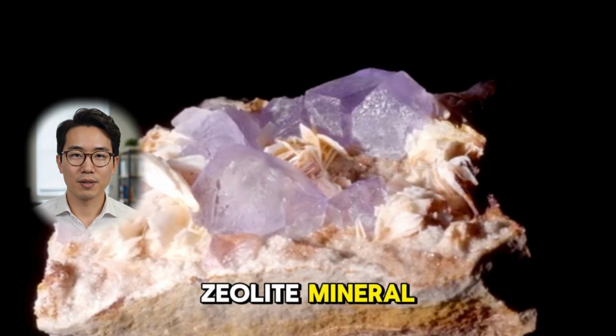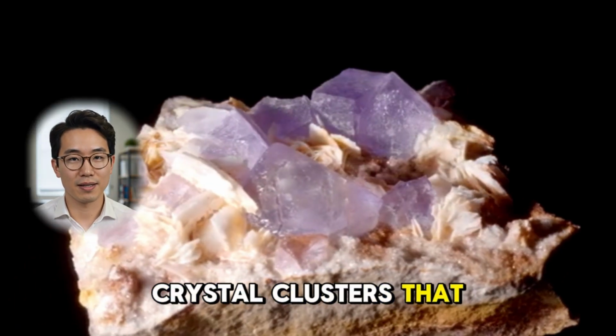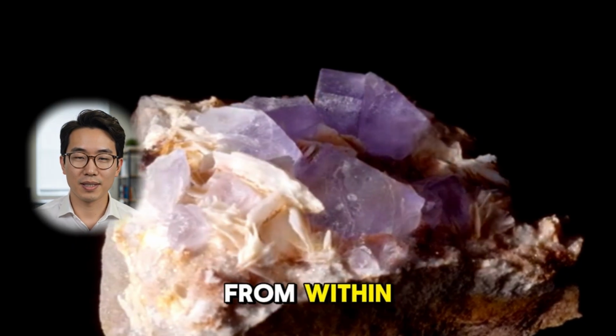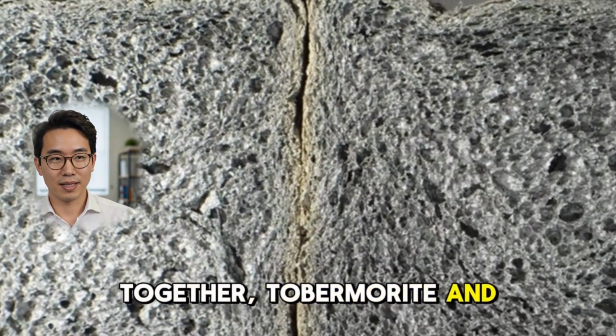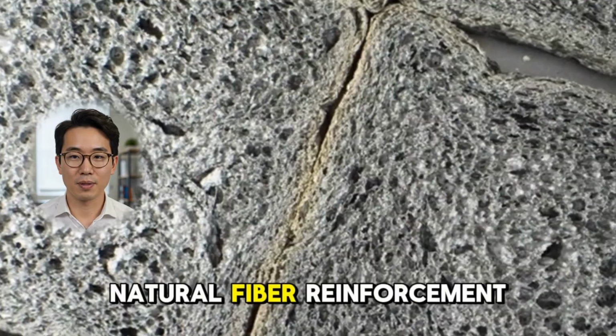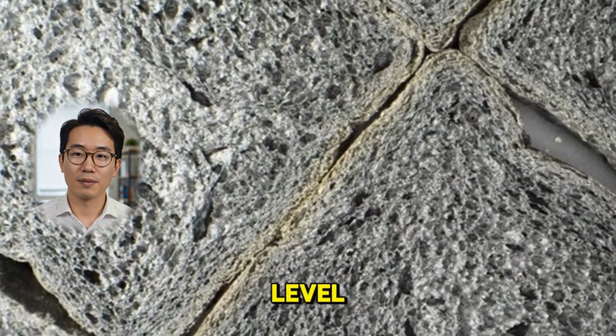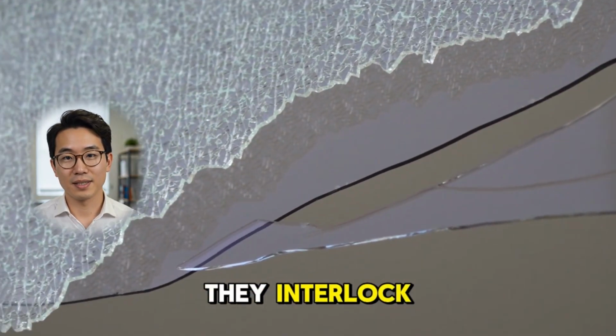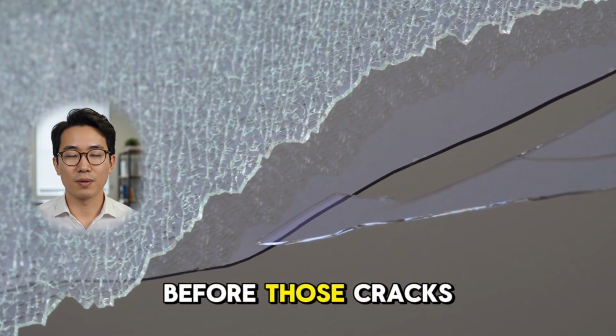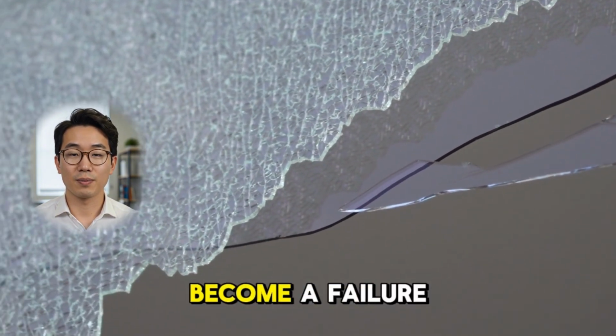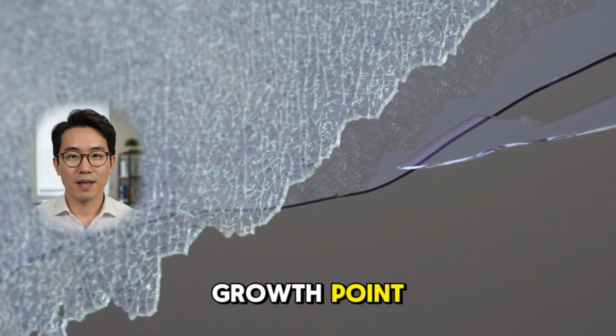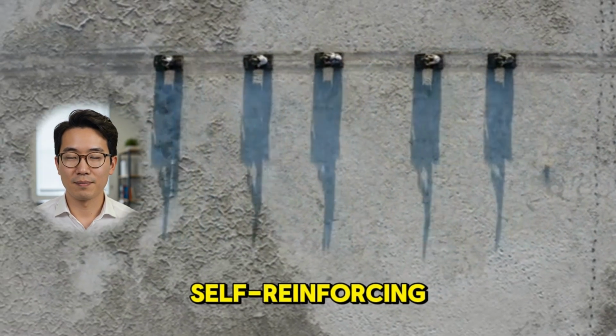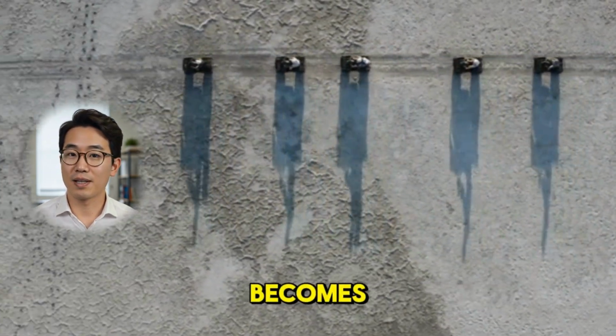Philipsite is a zeolite mineral. It grows in radiating crystal clusters that fill voids and reinforce the matrix from within. Together, tobermorite and philipsite function like natural fiber reinforcement at the microscopic level. They do not just fill space, they interlock. They bridge microcracks before those cracks can grow. They convert what would become a failure point into a growth point. The concrete becomes self-reinforcing. The longer it sits in seawater, the harder it becomes.